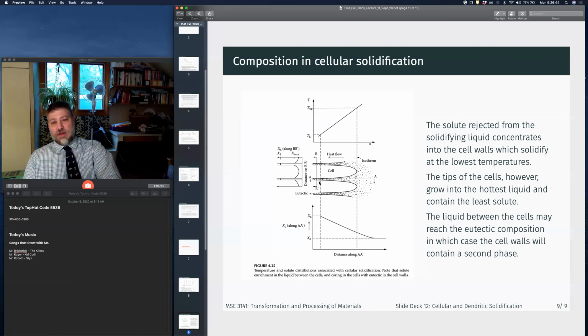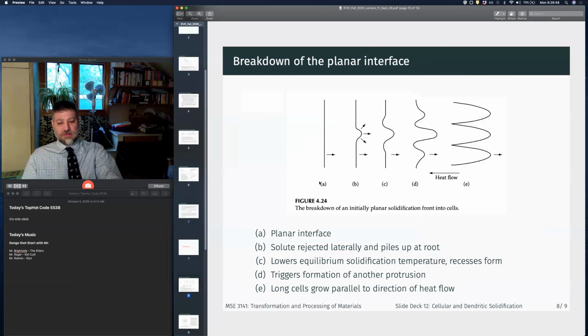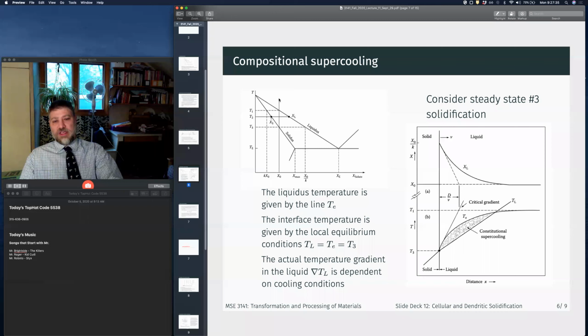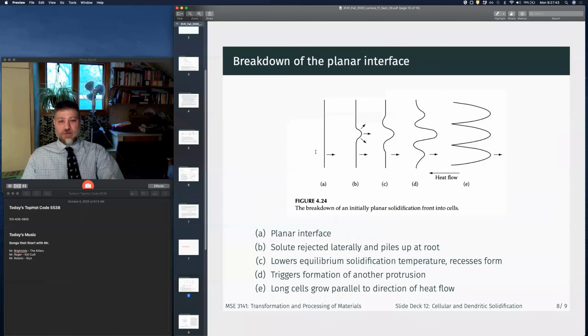As these grow. So, quick question. A larger planar solidification front leads to more compositional supercooling. Is that the relationship I'm getting from this? I'm not sure what you mean by larger planar solidification front. Planar solidification fronts are created when solute is rejected and piles up at the root, correct? Yeah, we have a planar interface here, and we're rejecting solute in front of this interface. What I was trying to say is the more solute rejected, the larger the compositional supercooling is going to be, right? Or another way of thinking about that is the larger this equilibrium freezing range is, the larger your compositional supercooling is going to be.